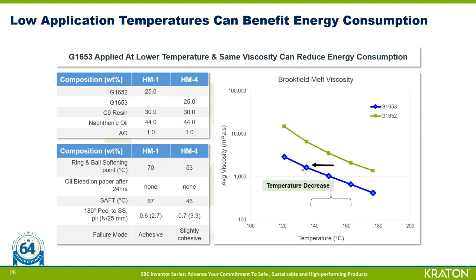So for example, in the personal care application, the effects of reducing the basis weight of the materials or making products thinner may now be more sensitive to application temperatures for hot melt-based systems. So in this case, the low viscosity of G1653, again the blue line, was leveraged to reduce the application temperature some 30 degrees Celsius, as can be seen in this graph on the right, compared to a G1652 based material.